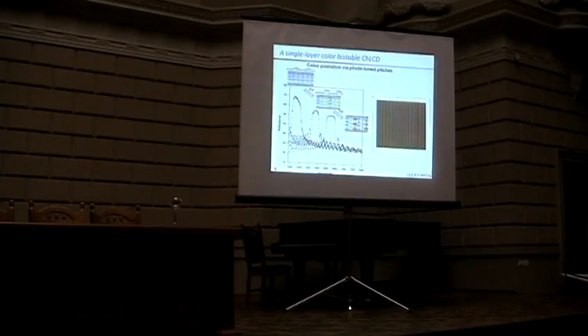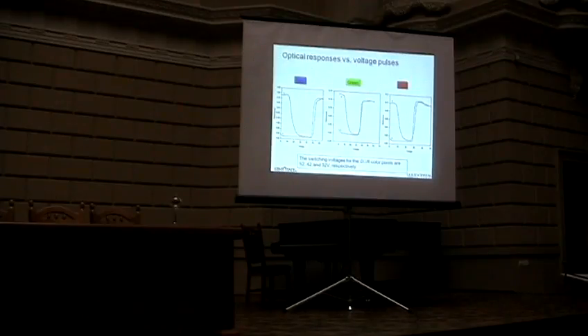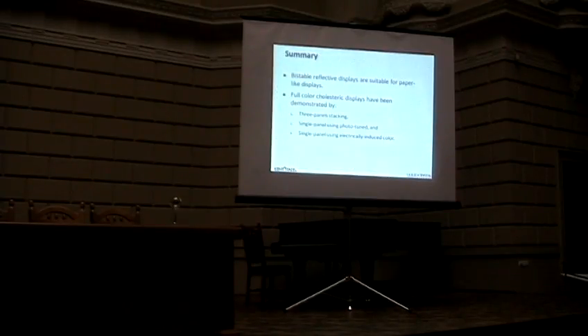For the color pixel, it's a single substrate that can be tuned. And here is the electro-optic effect, just like the previous one I showed you. You can switch from the reflective state to the transmissive state. But because the materials are different, with the lower pitch dopant here, the switching voltage is much lower, about 32, but for blue it is much higher. So there's a differential switching voltage. But this can be overcome by engineering methods. We can talk about this later, or I can answer your question.